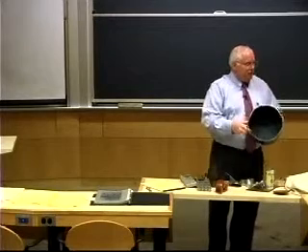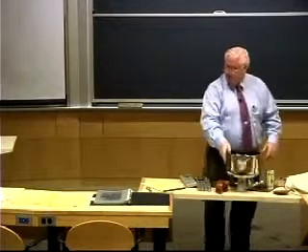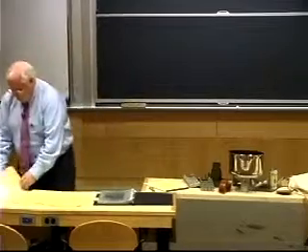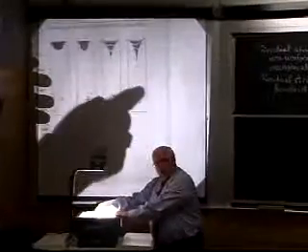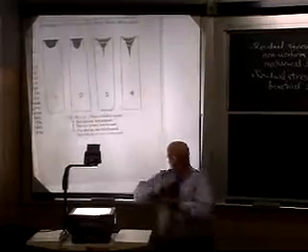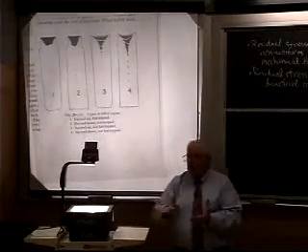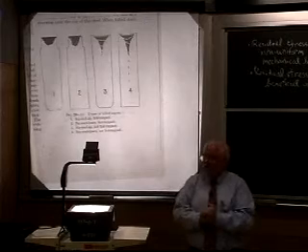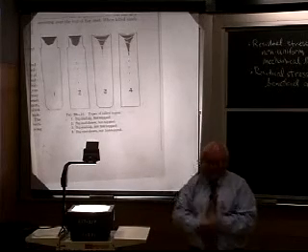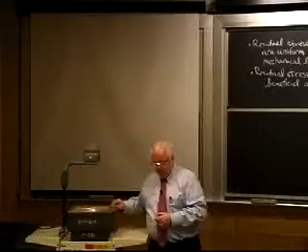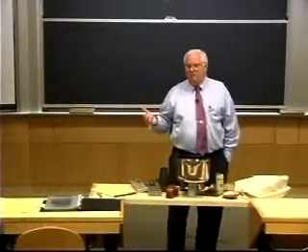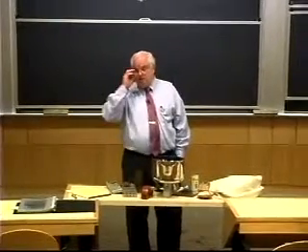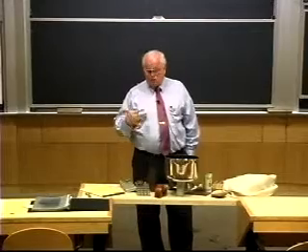I could have a huge flaw as a lamination in that plate, because of these types of defects that might be in the casting. I've got to do enough rolling and forging to close them up and weld them together. In the welding course, you'll hear about what it takes, but typically it takes 80 to 90% reduction. And so people have been trying for 100 years or more to come up with better ways to reduce the flaw size.